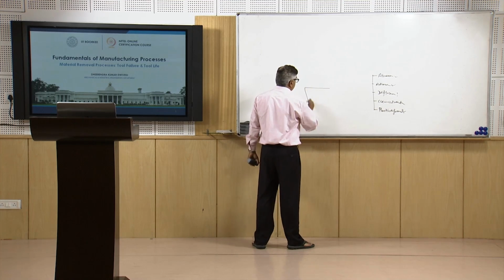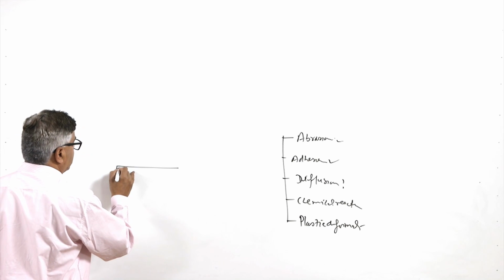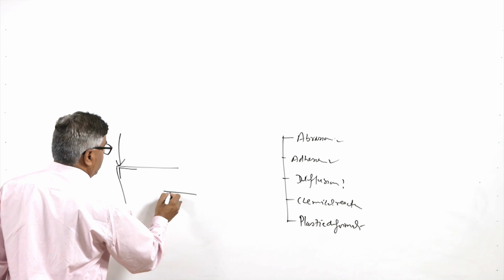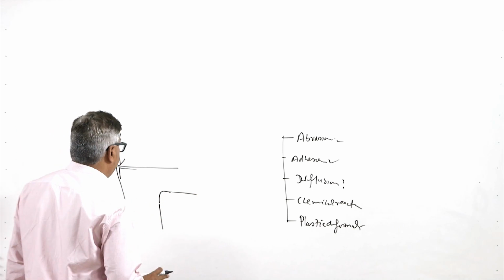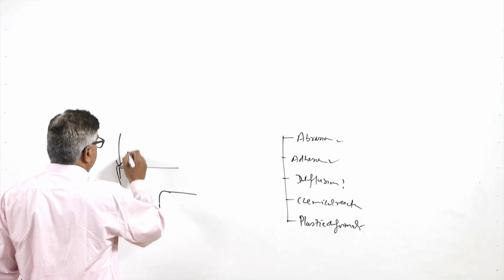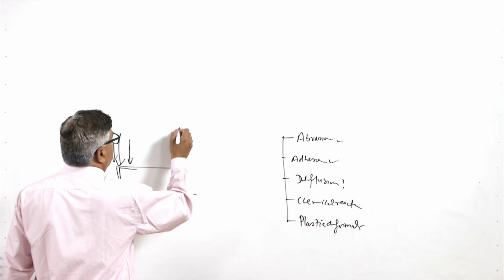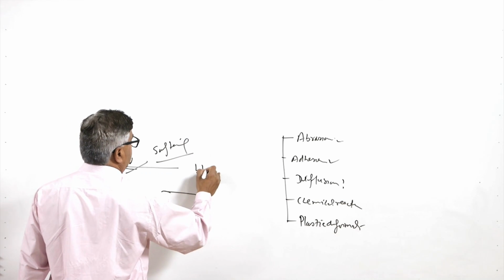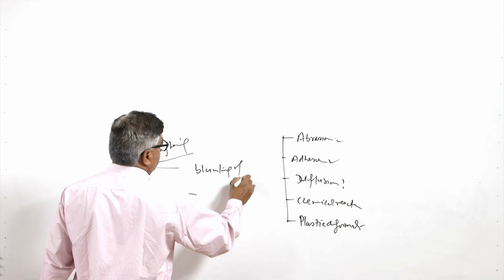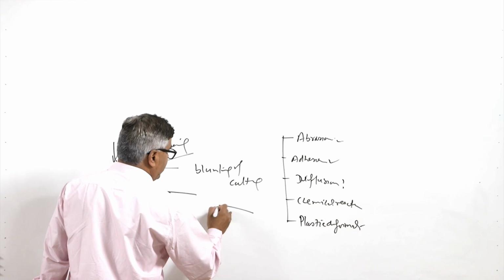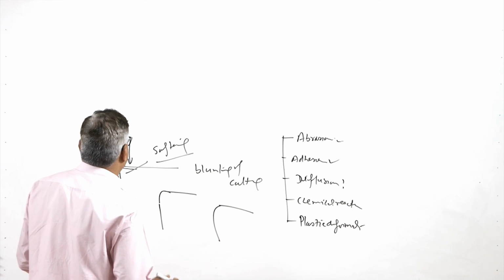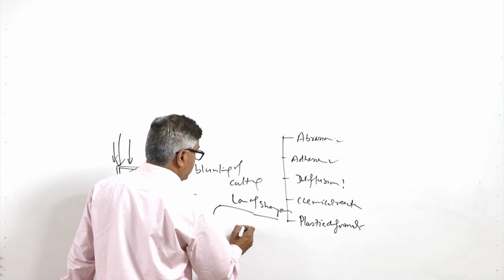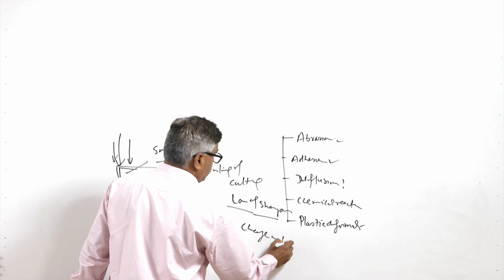Deformation is the case when the rise in temperature near the cutting edge is too high, then under the cutting forces, the cutting edge tends to get blunt or get deformed. Under the cutting forces acting during machining, rise in temperature will cause softening of the cutting edge. Softening will lead to blunting of the cutting edge, and blunting will lead to an increase in the radius of the cutting edge, which means loss of sharpness as well as a change in the tool geometry.